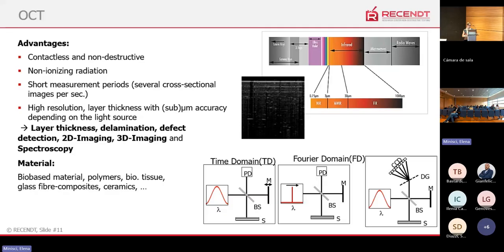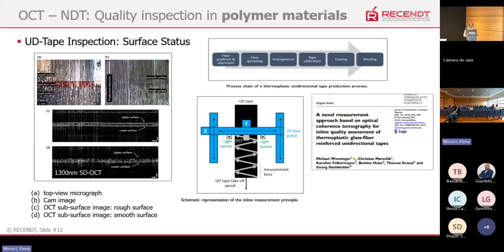And we can do fast imaging with short measurement periods of several cross sections per second. And also in special cases, we can make spectroscopic imaging with OCT. Here we have an example for quality inspection of a polymer UD tape where glass fibers are embedded in a matrix. And we want to scan during the whole production process at a special place to find out if the glass fibers are bundled or flat over the whole tape, and give some input back to the machine to go slower or faster. And we can see if we have a rough surface or a smooth surface over all the glass fibers.